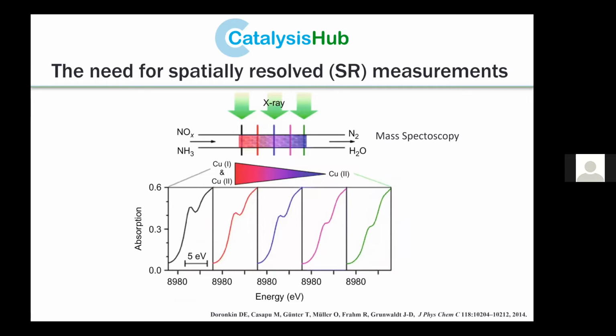Well, when you use simple single-spot analysis, you may start to form an idea of what your activity relationship is, but this may be highly dependent on where you're observing. Here, for example, you observe that the center has a completely different behavior than if you look at the start of the catalyst or at the end of the catalyst. This may have a strong effect on the structure-activity relationship we are trying to understand, because as you know, there may be a temperature gradient as well as a gas concentration gradient across the bed, and this makes the analysis not as straightforward.